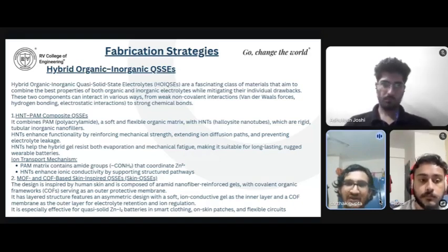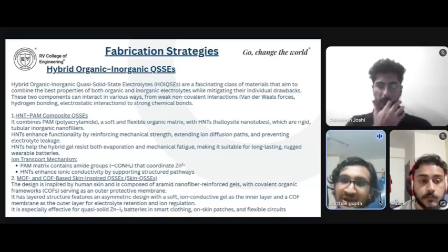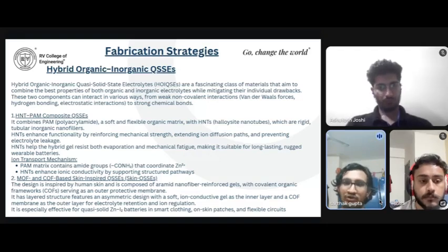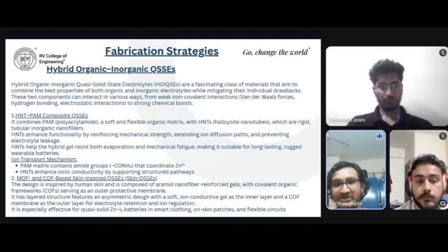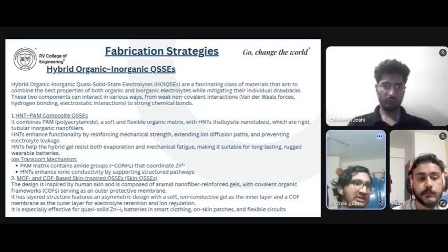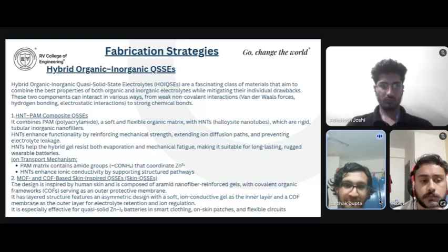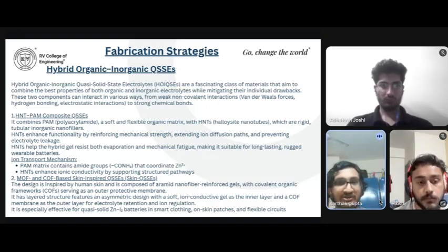These COFs have nanoporous channels that selectively allow zinc to pass, like how in a lithium cobalt battery the SEI layer allows only positive ions to pass. So these COFs have nanoporous channels that selectively allow Zn2+ to pass while blocking polysulfide shuttling. This is one of the drawbacks of various batteries which use sulfur in their anode or cathode part. So it also blocks that polysulfide shuttling, in Zn-I2 batteries also.